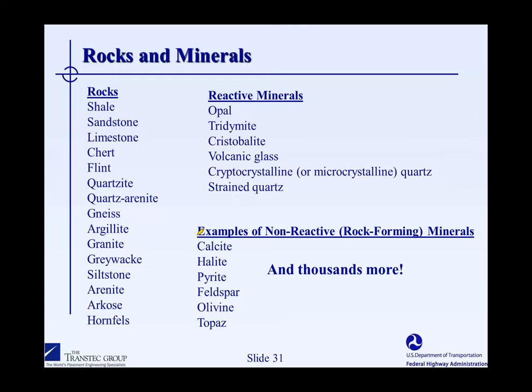So if we were to consider something like a granite, is it reactive or not? Well, a granite will contain many phases. It might contain some feldspar, for instance. But what will determine if a granite is reactive or not is how much strained quartz or even cryptocrystalline quartz can actually be found in that granite. So some granites will contain very little of these reactive minerals and they won't be reactive. Some granites will contain none. Some granites will contain more and they will be deleteriously reactive in concrete.